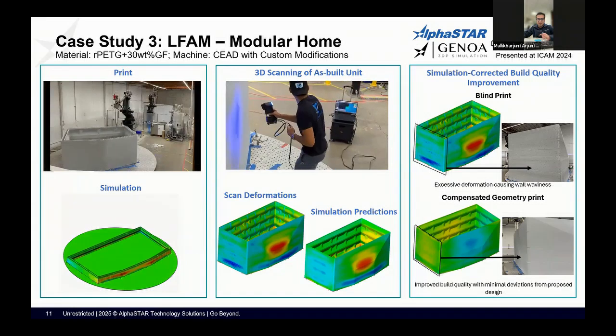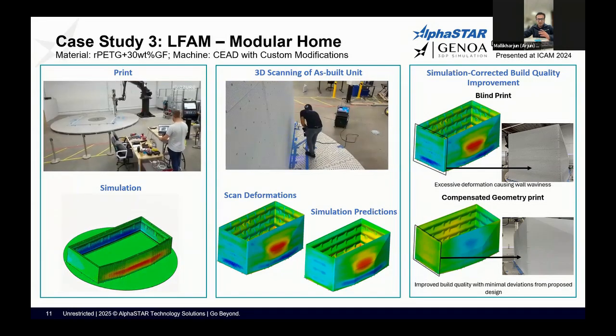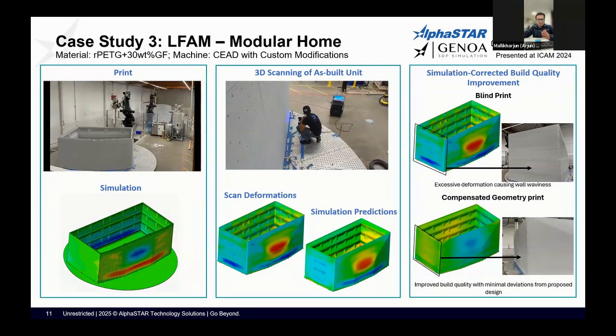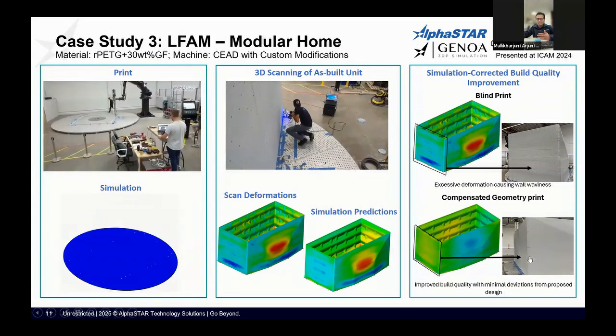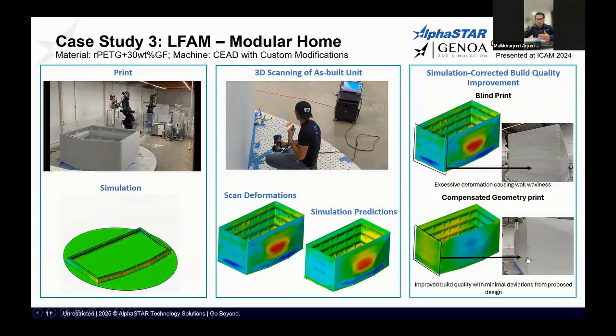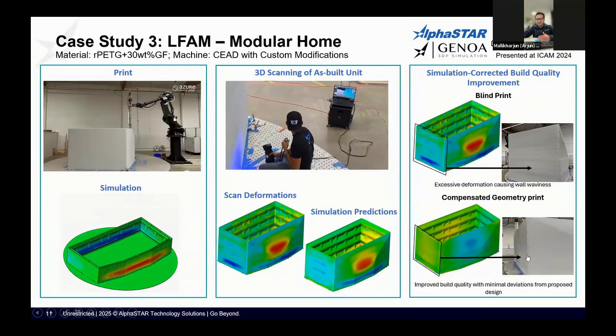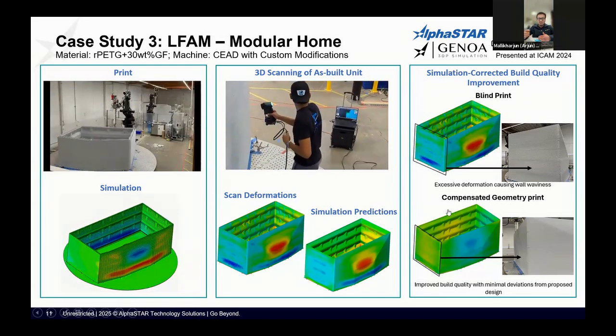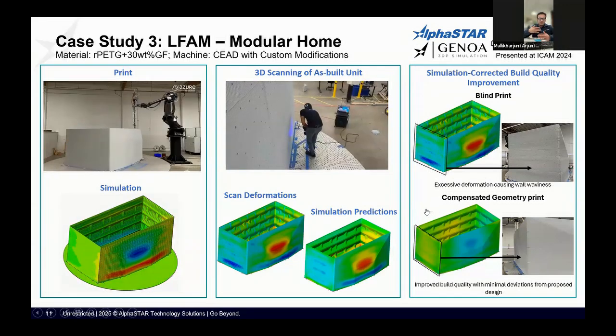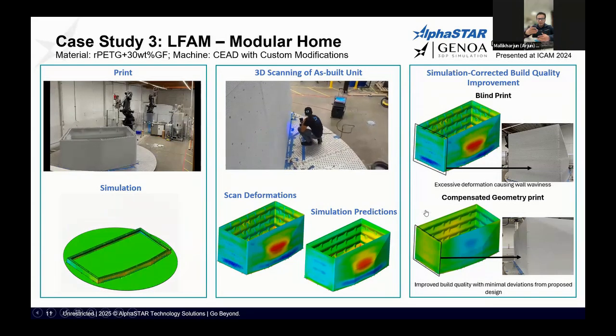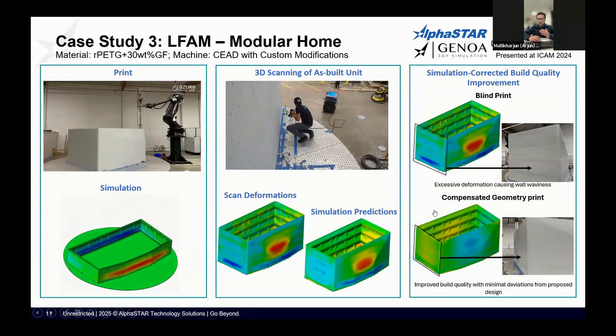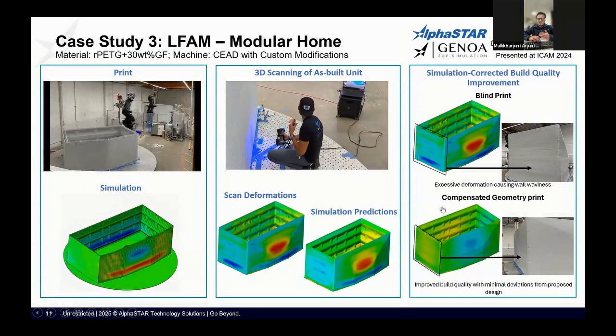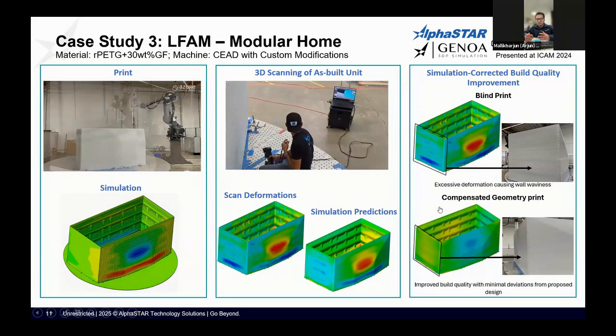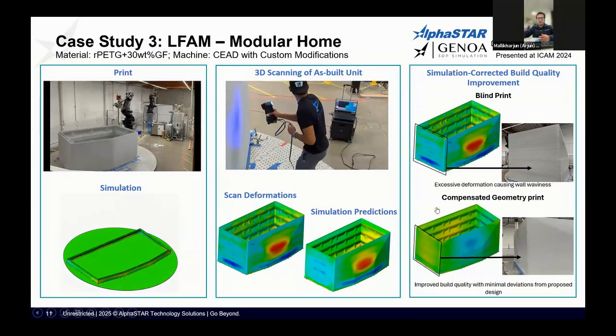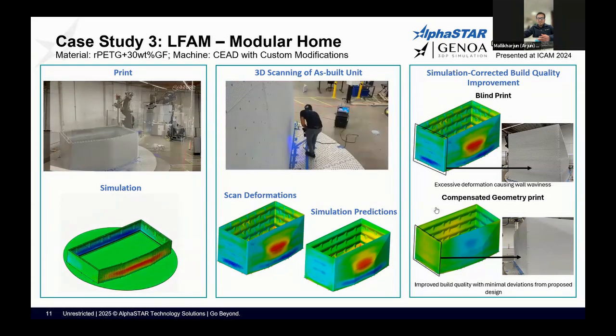So with, again, one round of iteration, we're able to show that, yes, instead of spending 15 to 20,000, how about you simulate it, which once we customize everything, it's very easy to simulate. You simulate, you compensate, and then you're able to reduce most of these warpage and deformation issues that you are getting when printing these structures. And one good thing is, obviously, this is our first round of iteration, but how about we create a virtual loop, instead of doing it physically, so that you can not only improve the quality, but also make informed decisions when you're designing these structures, keeping in mind the deformations and also the stress aspect as well. That is the overall value of implementing this ICME-based additive manufacturing solution.